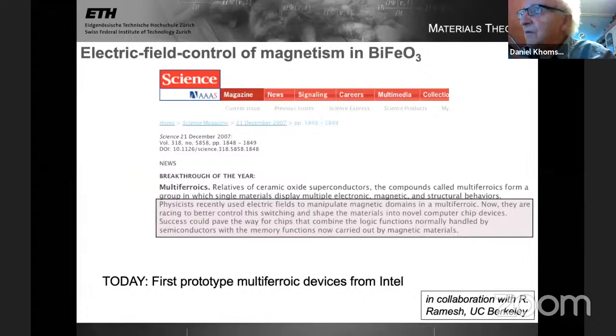So the exchange, the super exchange, is certainly determining the type of the magnetic ordering. And the second question, which was typed, but unfortunately I don't see from whom it is: if there are antiferromagnetic domains in bismuth ferrite, what is causing the energy gain in this sample? It cannot be the magnetic stray field as in a ferromagnetic sample. Can I find out what energy is favoring domain formation?